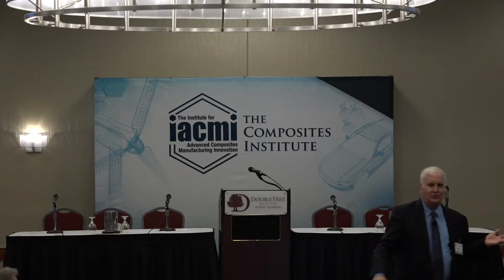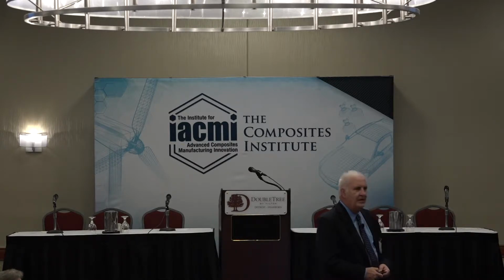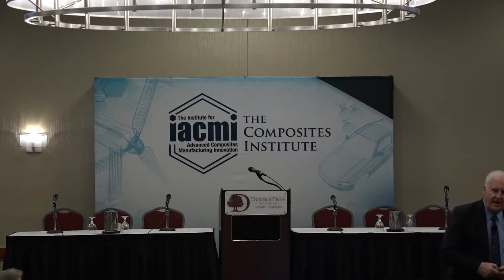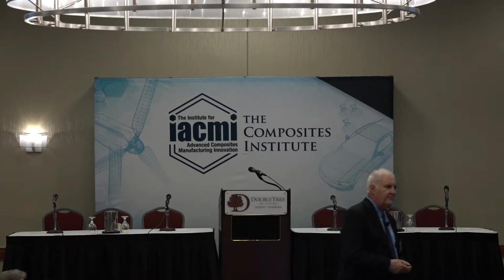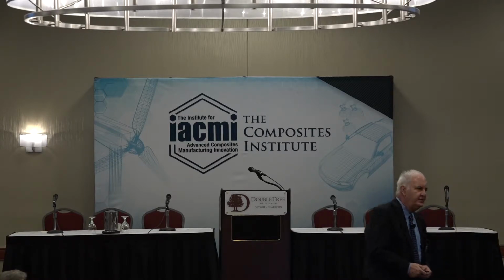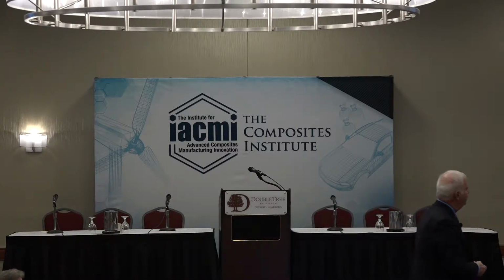So, I have about 25 minutes left. I'm going to cut to the chase here and tell you what our team demonstrated. We demonstrated a prepreggable vinyl ester carbon fiber system that contains no styrene, that has a long shelf life at room temperature, no need for refrigeration, fast cure and compression molding, an improved resin fiber interface and mechanical properties, a reduction in the amount of processed scrap that needs to go to a landfill, a reduction in embodied energy, and you all add all that up and you end up with a cost-effective system. I'm going to tell you about each of these sub-bullets in the next 15 minutes or so.